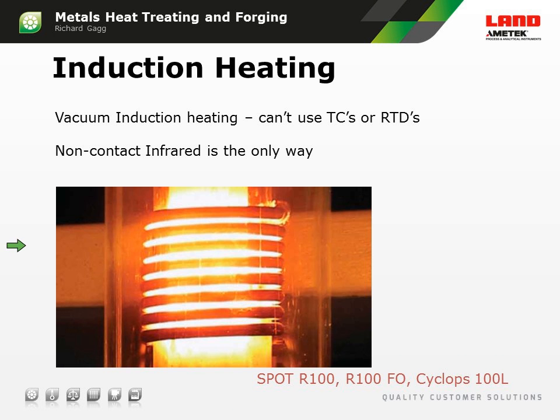Okay, here's another induction heating application. Again, ideally suited to non-contact temperature measurement. You can't put a thermocouple anywhere close to this. The second thing is, if you look carefully at this, you'll see in this particular case, this is in a vacuum. There is a quartz chamber around this with a vacuum atmosphere, and then there's the induction heating coil inside that.